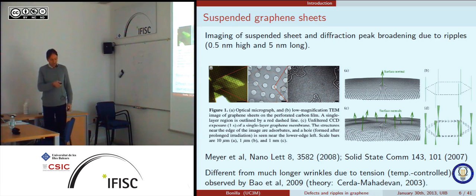And if you tilt it, you'll see that the spots become wider. That is because what you are seeing is the average of these things. So if there are ripples, the normals to the planes move a little bit. When you don't tilt, you see smaller spots, but if you tilt it, you see these spots are bigger, and that's a sign that the sheet is rippled.